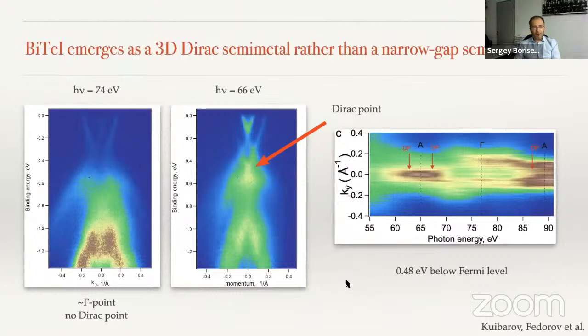Finally, we thought, well, why not try to detect the 3D Dirac points directly? And then, since we know the inner potential, we did the photon energy scan at the kinetic energy where we do expect these features. And we saw that using 66 eV, we see the Dirac point. Using 74, you don't. Then you plot it on the map, and you see that the Dirac points are shifted towards the A point. It's not exactly as in calculations, sitting in the middle, but they are shifted towards the A point. But we continuously see that they are present in the vicinity of the A point.